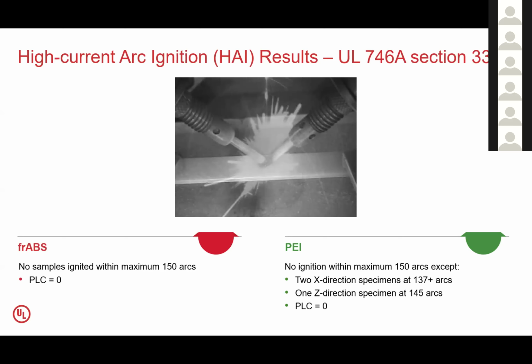With the polyether imide, again, we saw a very similar type of behavior. Out of the 150 specimens that we tested that were 3D printed, 3 of the 150 did ignite. Again, it was at such a high number of arcs occurring that it still leaves that print as being considered the best performing category. So we can look at 3D printing where it was significant on flammability tests. On a high current arc ignition test, we don't see a significant result impacted by 3D printing.